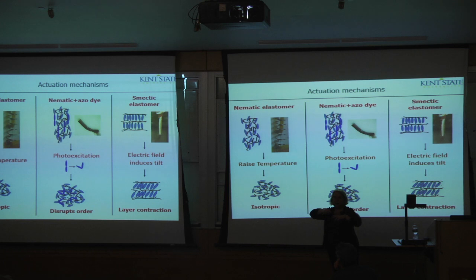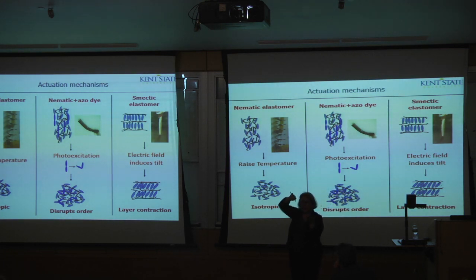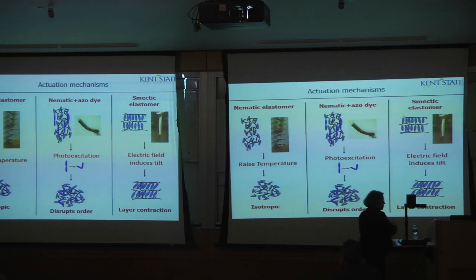It turned out that was because when the material was cross-linked, there was a little asymmetry. The polymer is formed between two pieces of glass that align the liquid crystal. They put the liquid crystal, the monomer, and the cross-linking agent between the two pieces of glass, and then they shine UV light on it to polymerize it. If the top gets a little higher cross-link density than the bottom, that asymmetry is what turns what should be a stretch into a bit of a twist. So it's the asymmetry that drives that one.